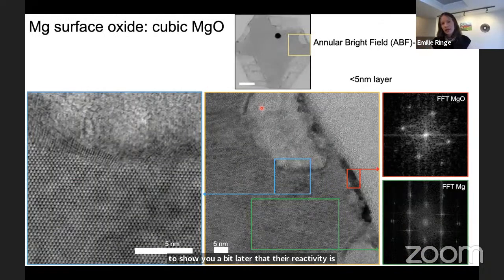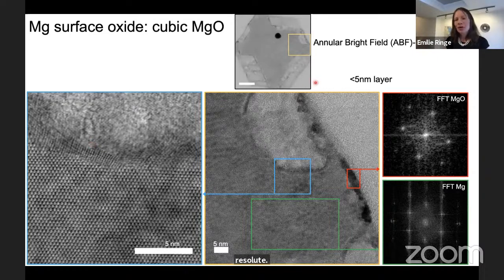An easy way to show you that there's oxidation is a good old high resolution STEM image. So this is an annular bright field STEM. It looks kind of like a high resolution TEM image. And basically what you see is the atomic packing here of the magnesium metal, which is hexagonal. And then that's coated by a thin layer of cubic MgO.